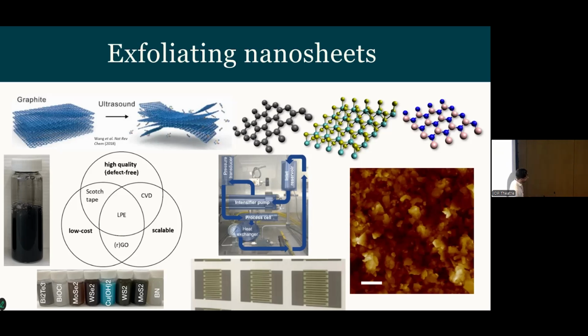So with our pilot scale process, we decided to do some of that work and work out whether it had to be graphene, or indeed in this area whether there was any benefit of exfoliating and size selecting down to near monolayers. So we use a technique called liquid cascade centrifugation, which is successive centrifugation steps. We sediment the samples successively, collect the sediment as the sample, and take the supernatant onto the next centrifugation step. And that's smaller particles, thinner particles. They're inherently coupled for these systems.